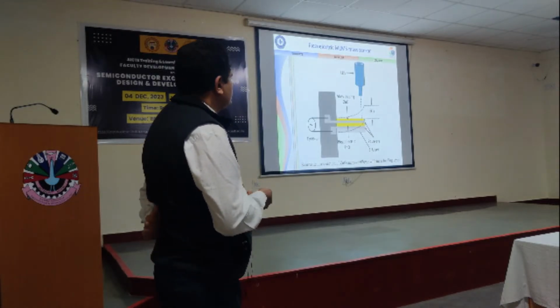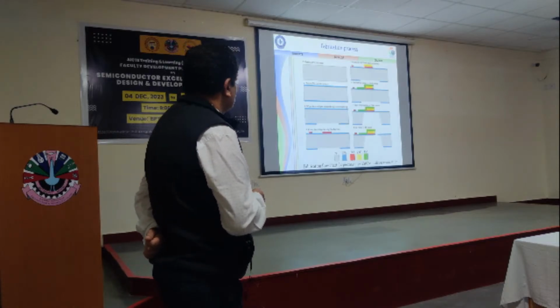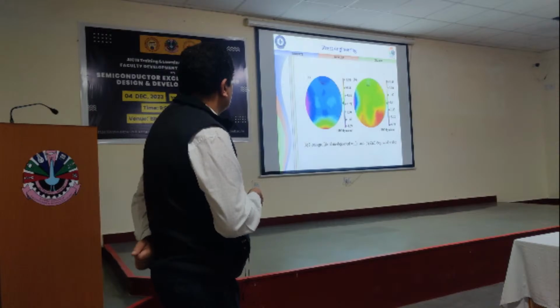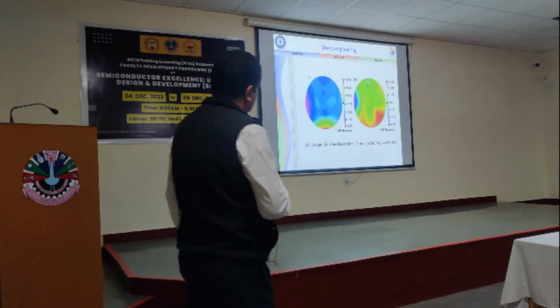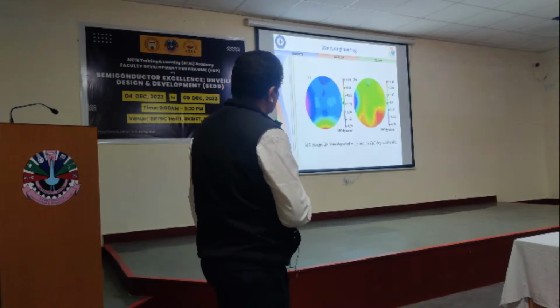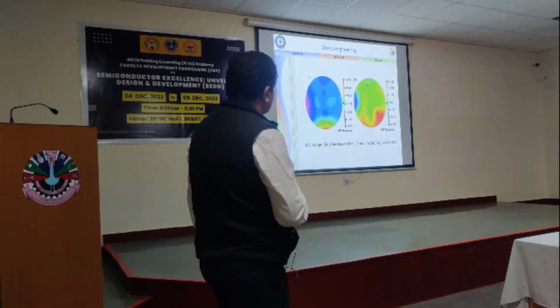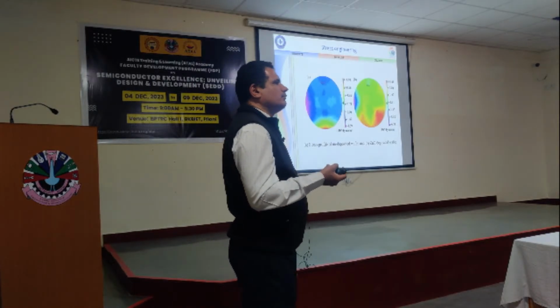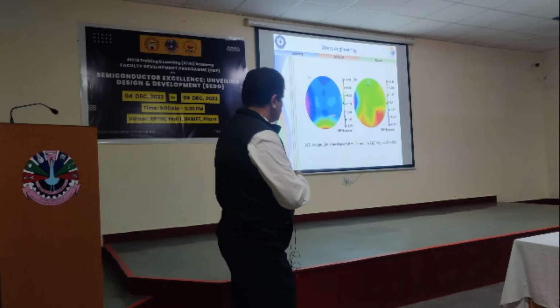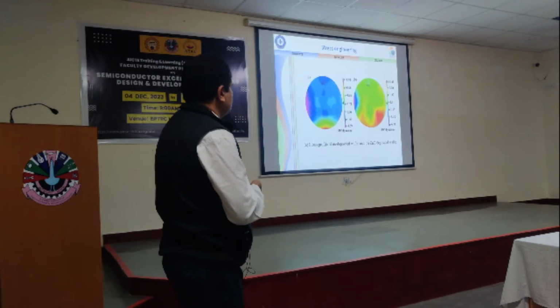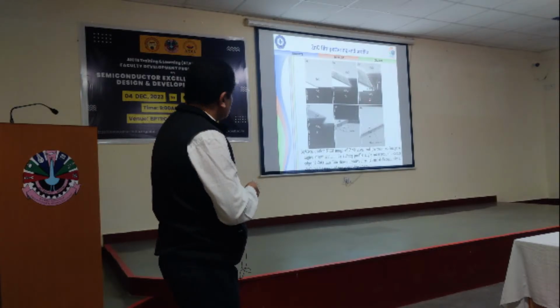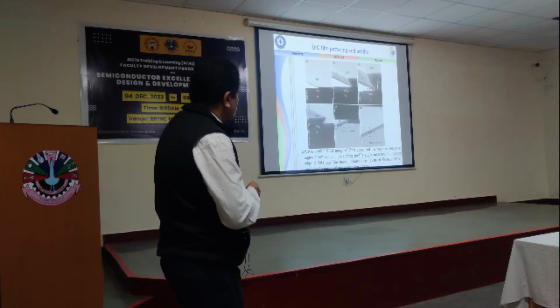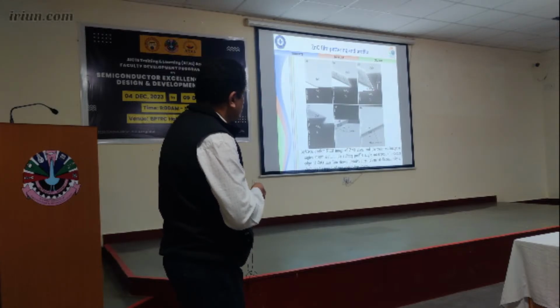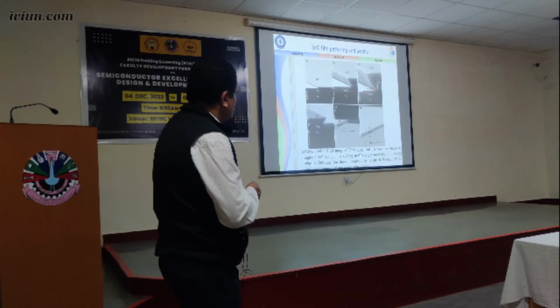Also we did some mass sensor work using the micro cantilever fabrication process, and we did the stress engineering of it. Stress means we did the silicon dioxide, we did the zinc oxide deposition, and the stress profile was measured. Means my device should be reliable and repeatable. So I have to do stress engineering so that the device can be made better. These are some of the zinc oxide deposited and their stress after etching. How does the profile look after etching of zinc oxide? The profile makes some angles with your underlying layer, and that was measured here.